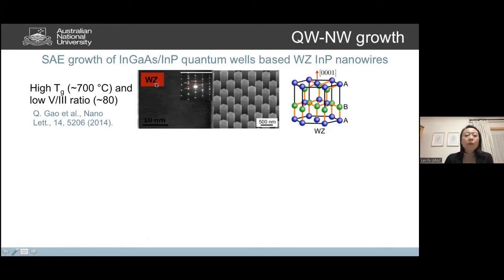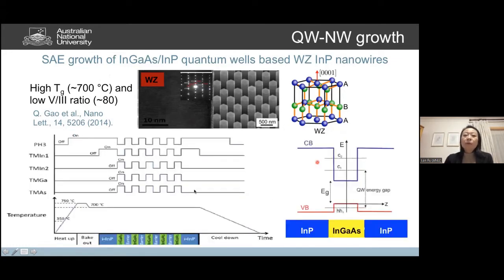basically when we grow the indium gallium arsenide, indium phosphide nanowires, as I mentioned before, for a wide range of applications, we normally use selective area growth at high temperature, about 700 degrees C, and a low V/III ratio, where we find that the structures are mainly based on wurtzite indium phosphide, which is a hexagonal lattice. And then when we start to grow indium gallium arsenide quantum wells, we thought that would be quite simple. What we do is that during our growth, we switch off the indium phosphide source, basically switch off the phosphine, and switch in the gallium and arsenic sources. We'll be able to just grow indium gallium arsenide, because the quantum wells are normally very thin, just a few nanometers.